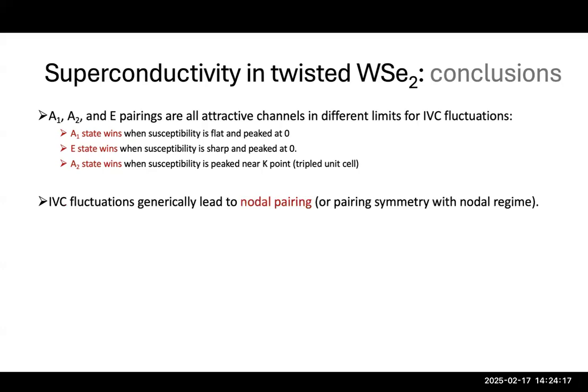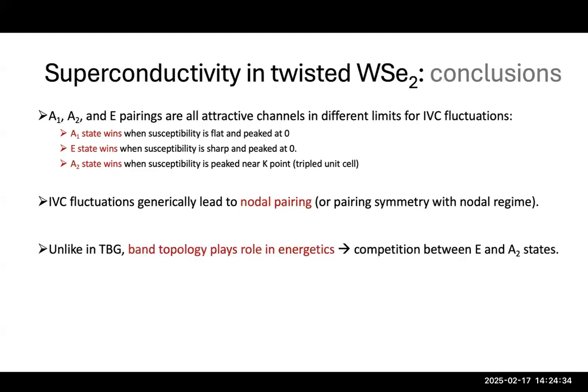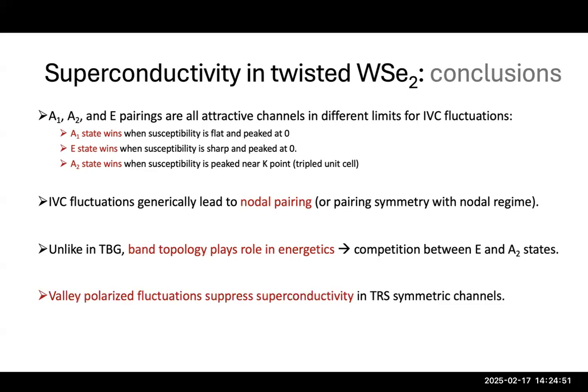So in general, for all of these cases, IVC fluctuations generally lead to a nodal pairing, or a pairing which has a nodal regime depending on, I guess, the amount of displacement field and breaking of the symmetry between the even and odd parity pairings. And we saw that unlike in TBG, because your leading instabilities all generically have a sign change for IVC fluctuations, there's an important role being played by band topology and the energetics, which leads to competition between the E state and the A2 state. And that valley polarized fluctuations suppress superconductivity in all the time reversal symmetric channels.